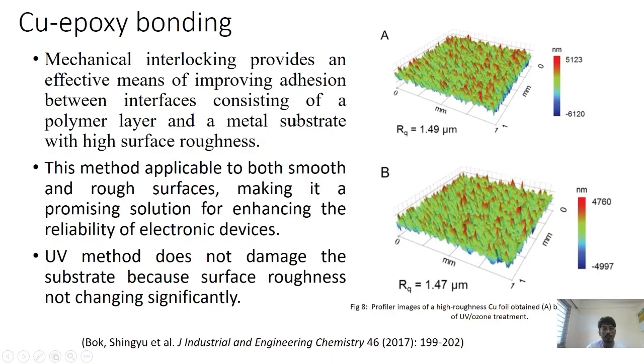The copper substrate, which is a metallic object, can have two types of surface roughness. One is higher surface roughness, the other is lower surface roughness. Generally, with higher surface roughness, adhesion is achieved by mechanical interlocking between the copper and the epoxy. But in low surface roughness, with a surface roughness of 0.1 micrometer, there is less roughness, so mechanical interlocking is not significantly possible. So we introduce a UV or ozone method, which is used for increasing the adhesion strength between the copper and epoxy. The UV method also does not damage the substrate, because surface roughness is not changing significantly.